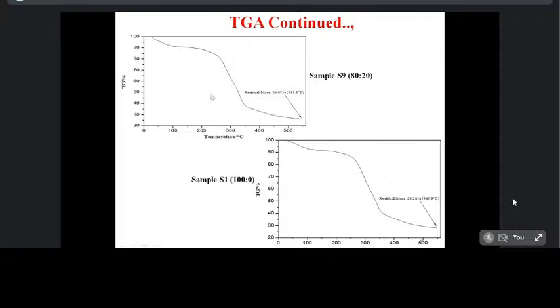A single stage decomposition is observed, mainly due to the reduction of mass of the sample. In this single stage reduction, carbon is converted into carbon dioxide and carbon monoxide. The loss of mass of the sample gradually reduces due to the reduction of the combustible substances. The weight loss was found to be 28.28% for this sample at the temperature of 547.9 degrees Celsius, which is mainly due to the presence of non-combustible substances and ash.